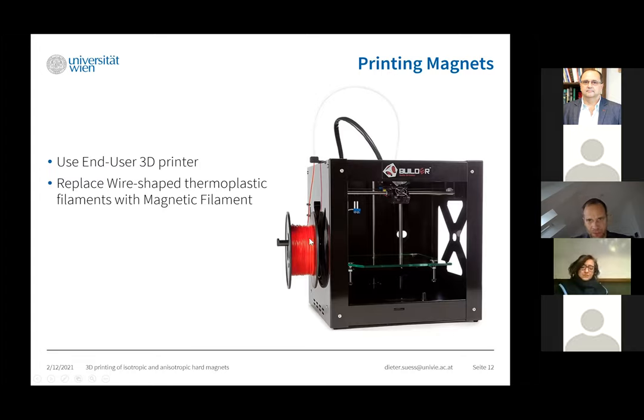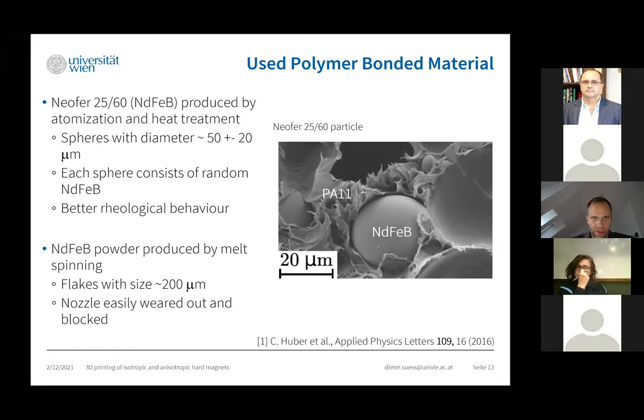What we did is we used a standard 3D printer and we replaced the polymer filament by a magnetic filament, where we started from Neofer 25/60 granules, which are a combination of neodymium iron boron particles embedded in a polymer PA11 matrix. These spheres, which are produced by atomization processes, are quite spherical, which is also quite good because it gives very good rheological behavior for the 3D printing, as well as for injection molding.